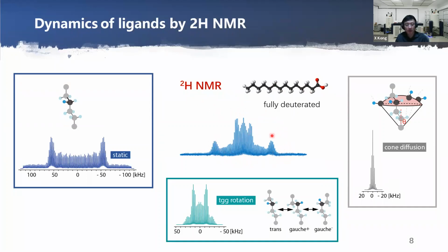This is an experimental quadrupolar pattern of the deuterium. This can be broken down into three different contributions. For example, the broad pattern corresponds to the CH2 unit under strong packing, probably in a glassy state. And also the cathedral-like pattern, a little bit narrower, corresponds to the CH2 undergoing trans-gauche rotation in a partial confinement. And also the sharp peak in the middle corresponds to the free CH2 undergoing something like cone diffusion. That means it is without any restriction.